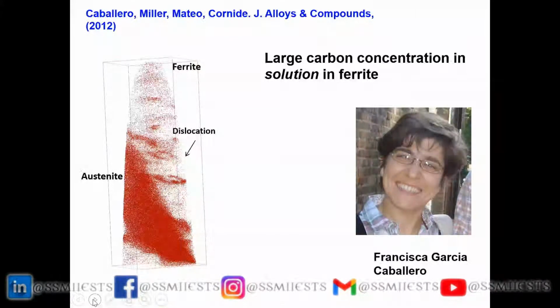This is Francisca, who did this work. And using the more sophisticated instruments, you can see the segregation to dislocations in the ferrite, but you can also see large concentrations of carbon which are in solid solution inside the bainitic ferrite. When I say large concentrations, it is up to 0.38%.